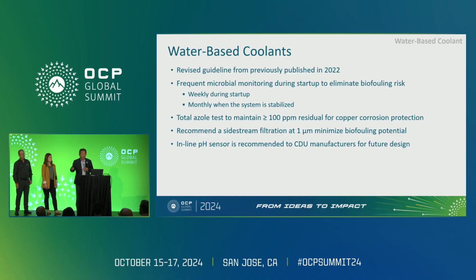Once it's started up, you check the coolant quality weekly, and if everything is stable, you can do monthly checks. After that, you just maintain the azole at or above 100 ppm residual for copper protection. For treated water, we recommend using a 1 micron side stream filter to keep the biofouling to a minimum. That's the biggest concern.